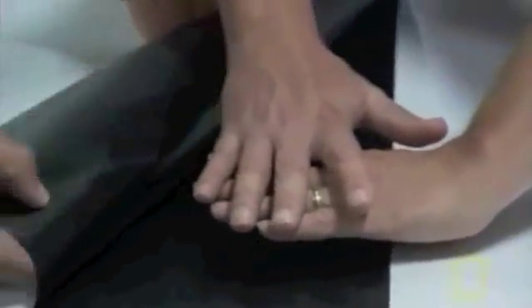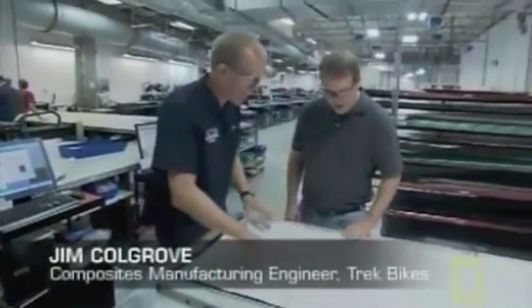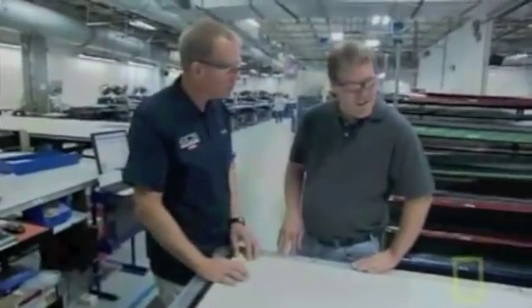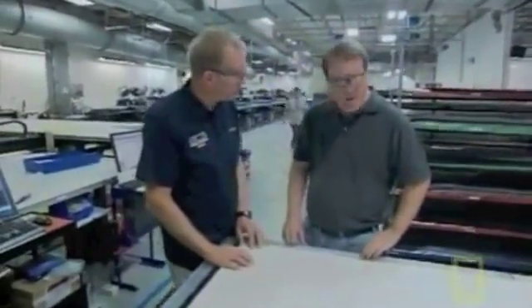This layer is going this way and this one is going this way — so it's like a ten-layer stack. All of our ply stacks are different thicknesses. In certain areas of the frame we may have only four to five plies of material; in other areas requiring greater strength, we may have upwards of 40 plies. That's how you save weight as you go across different parts of the frame.